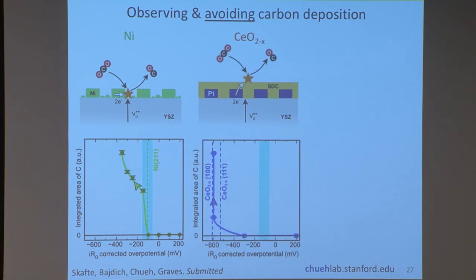The second material, which has also been investigated a lot for the fuel cell reaction, but not for electrolysis, just for the fuel cell. So this is converting, say, CO to CO2 or hydrogen to water. There, the behavior is very different. So if we only have this material, so cerium oxide, then you can operate the cell about 500 millivolt beyond its equilibrium and still get no carbon. So here, the blue line is where you expect the carbon to be deposited, so this is unwanted. But instead, you can push all the way south to 600 millivolt before carbon shows up. So this is highly desirable.